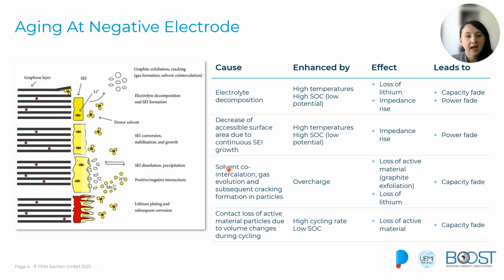Additionally, when we have repeated cycling in our battery, due to the expansion and contraction of the cells and of the anode material, and because of that expansion, contraction and the mechanical stress, it will also result in cracks in our negative electrodes and in the loss of electrical contact within the electrode structure. That will also increase the impedance of the cells and lead to capacity fade and power fade of the battery.